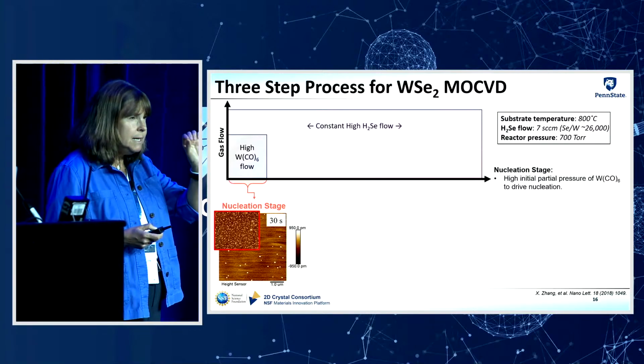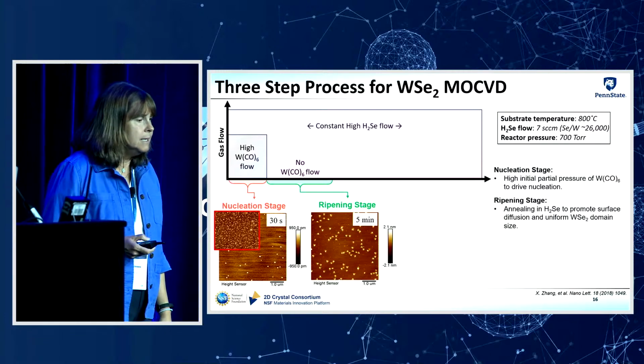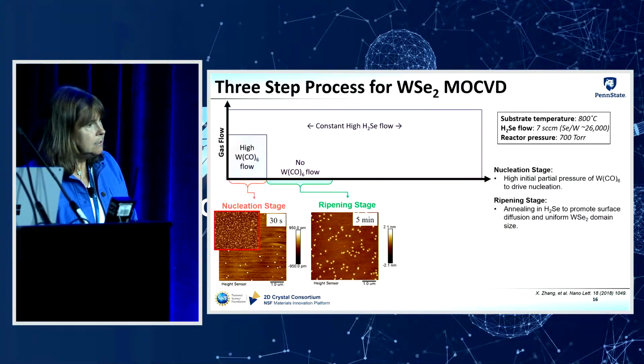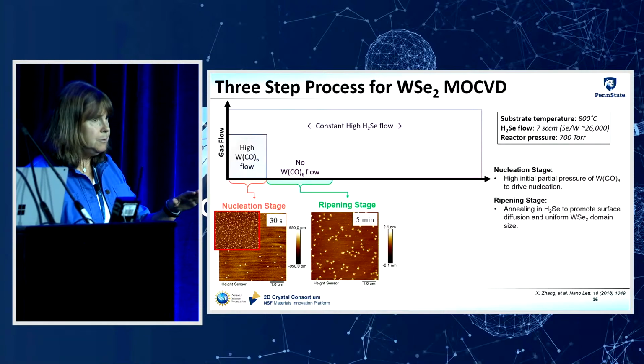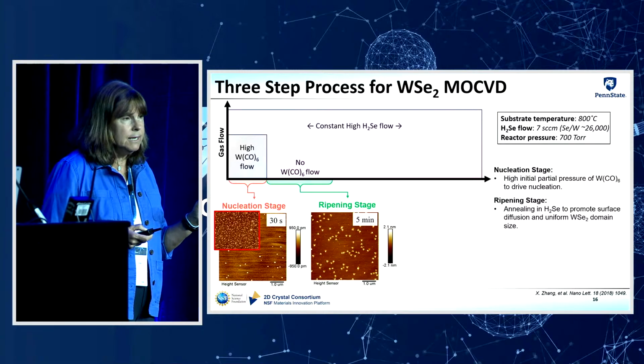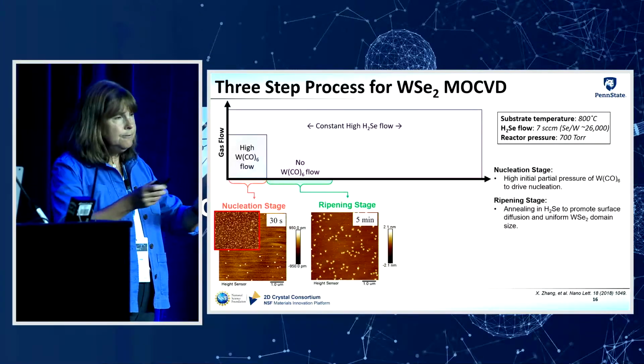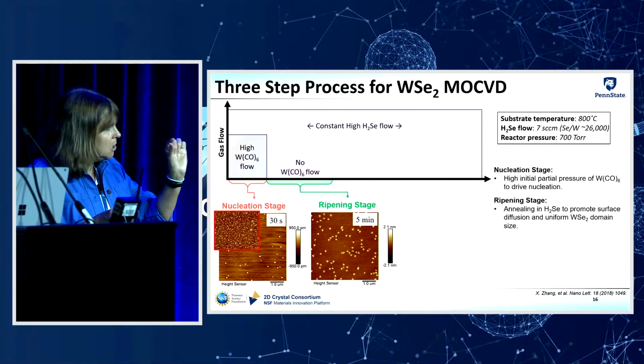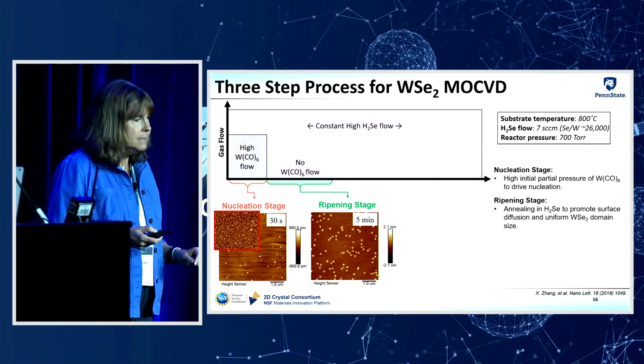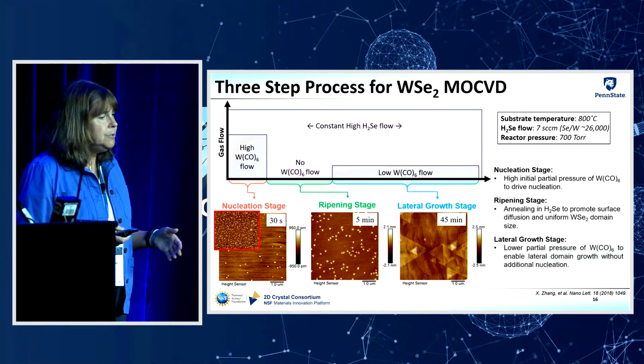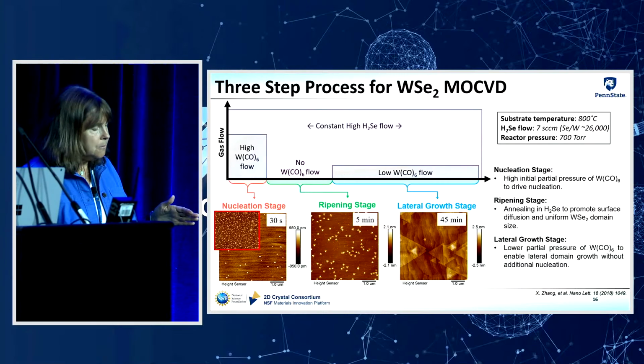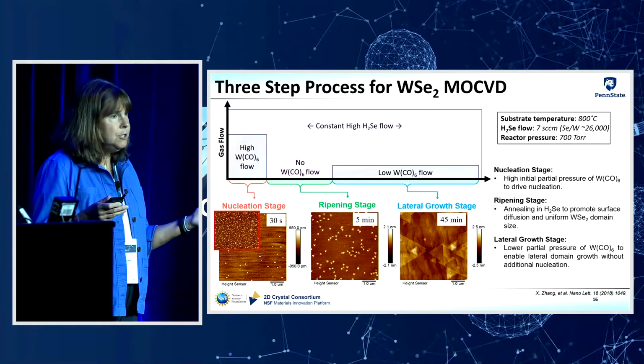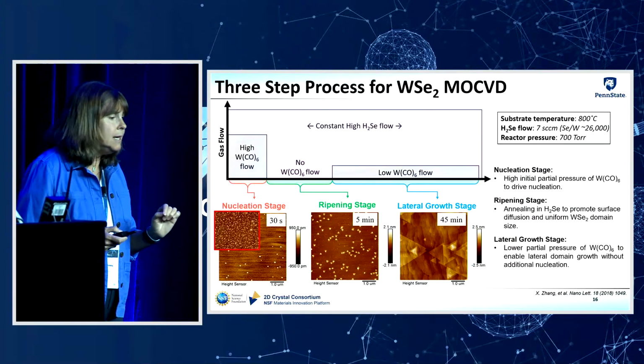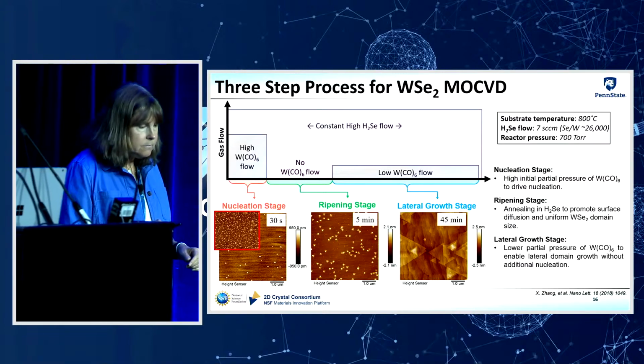And we end up with these tiny little clusters of tungsten diselenide. Then we switch the tungsten source out and just allow the substrate surface to anneal or ripen under a flow of the hydrogen selenide. These little clusters will diffuse around and form small, tiny triangular domains. Then we can reintroduce the tungsten source, but at a lower flow rate, so we can laterally grow the domains without getting additional nucleation occurring.